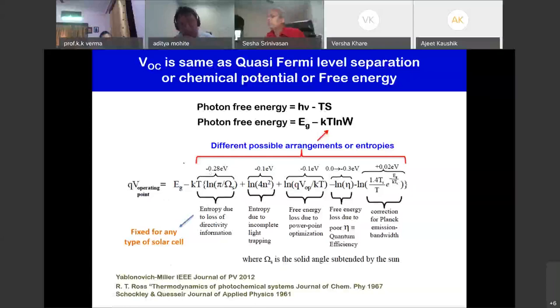So no matter what photovoltaic device you're making, whatever band gap you have, you just subtract 0.3 electron volts away and you just give it away. And that's why I call this the gift of God. You can't really do anything about it unless you're using a concentrator or some other special ways. Another loss that can be really big is entropy due to incomplete light trapping. So imagine you make a device and it doesn't trap light completely, then you can get losses associated with that. The minimum loss you can get is about 0.1 electron volts, so you lose about 100 millivolts like that.